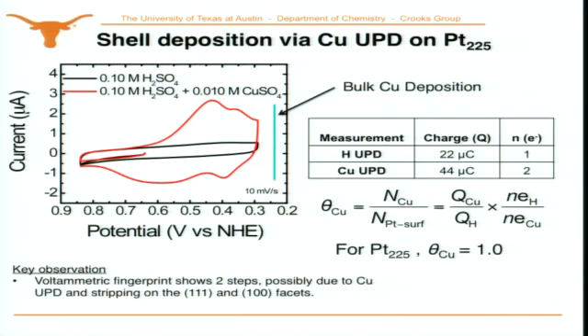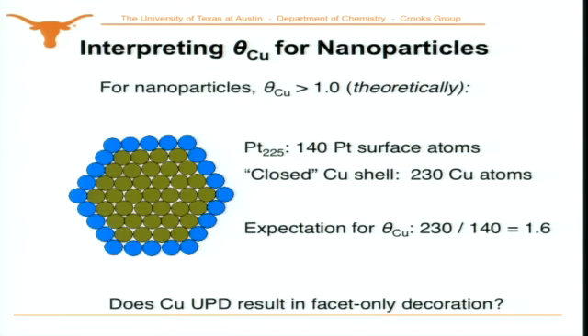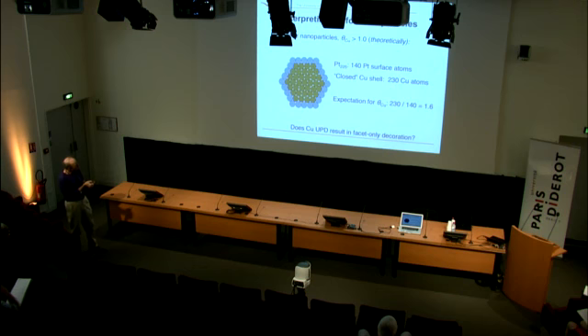Until Dave Yancey pointed out in our subgroup meeting where we were talking about this, it shouldn't be 1.0. It should be a lot bigger because these are not bulk surfaces. These are nanoparticles. And if this were analogous to bulk copper UPD, then we should deposit yet another shell around this, a close-packed shell around the outer platinum shell. Well, platinum-225 has 140 surface platinum atoms. So if it were a closed copper shell, in other words, if we just went to the next magic number up, the next closed shell, there'd be 230 copper atoms. And so the expectation for the nanoparticle is that theta copper should equal 1.6.